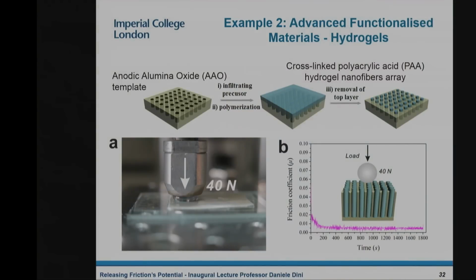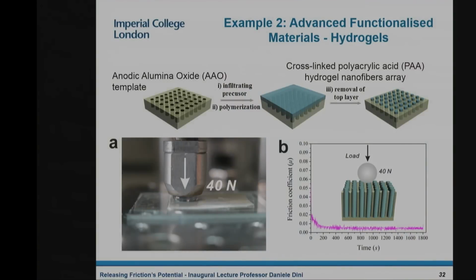So they took a system which has got pores, and they infiltrated this with polymers, and then they cross-linked these polymers to form a hydrogel. Now, when they cross-link this polymer to form a hydrogel and they peel off the excess hydrogel, they end up with a series of polymer heads, hydrogel heads, sticking out of the surface. Now, it turns out that if you put this material in contact and you try to slide something over it, if the liquid between these two surfaces has a certain pH, you can get very low friction. You basically don't need any force to make this thing slide.